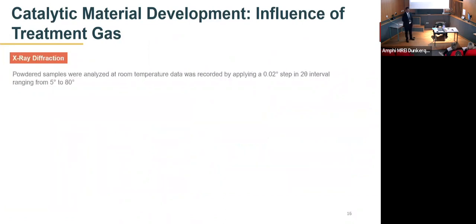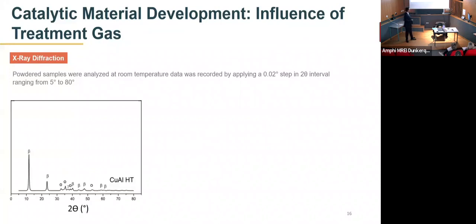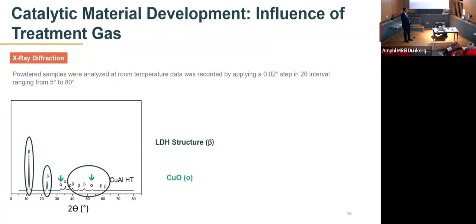The second material characterization technique that we used was the XRD, in order to know the different crystalline phases that we have in our sample. At first we did an XRD analysis for our parent material, which is the starting material LDH. Here you can see that we reached the LDH structure during our synthesis. However, we also saw some crystalline phases of copper oxide in our starting material as well.